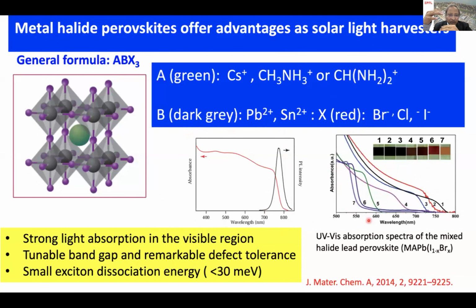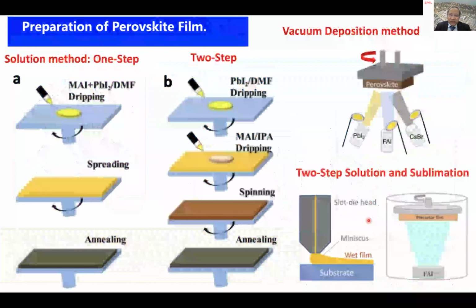The more important property of this material is the low, small exciton binding energy. The moment you shine the light, you create carrier charges, positive, negative, they go together. This is called exciton. This exciton binding energy is typically very high. In these perovskite materials, this exciton binding energy is very low. It's less than 30 millielectron volts. That's the reason why most of these materials are very efficient for separating charges.